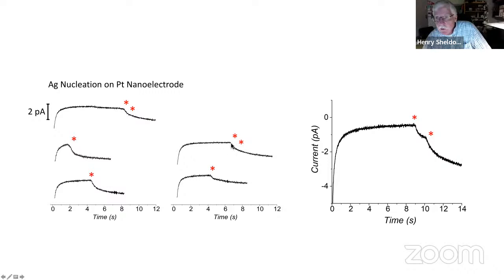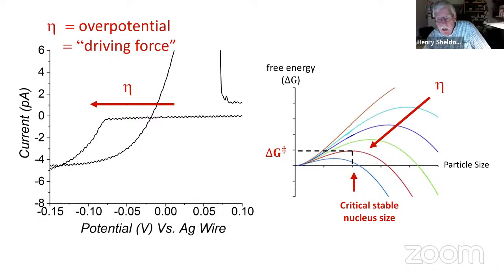The nice thing about this experiment is we can measure the time to nucleation. We can do this over and over, get hundreds or thousands of nucleation times, and then using a Poisson type of analysis, we can calculate the characteristic frequency of nucleation. What we're interested in here is understanding what happens when you change the overpotential. If I go from right to left here, I'm increasing the driving force for nucleating a particle. And this corresponds to this free energy curve over here. This is free energy versus the size of the particle.